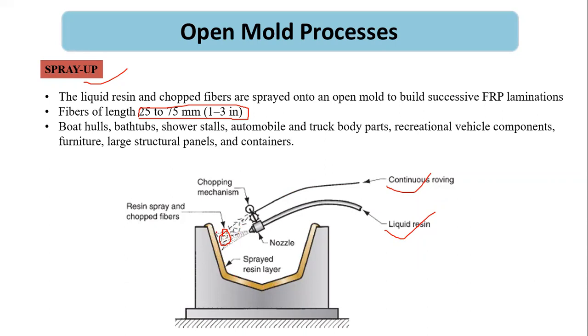Then at the end, you can use a roller to compact the fibers so that you get a highly dense structure. Otherwise, it will be porous and there will be air bubbles present in the material. Okay, and then once the rolling is complete, you keep it for curing, and then you remove it after curing. Okay, and the applications are again the boat hulls, bathtubs, shower stalls, automobiles, truck bodies. A lot of applications nowadays for composite material, because they provide lightweight and better strength. And if you want to say in a single term, that is the specific strength of the composite material, which is very high, and that is why it is a very popular material to be incorporated in various industries.